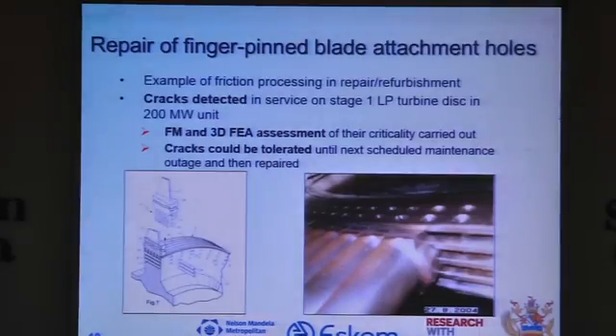The first case study I've got here for you is a repair of fingerpin blade attachment holes. We detected cracks on these discs. Did our fracture mechanics calculations, did our 3D FEA work, saw that the cracks are not critical, but they will be critical at the next shutdown. So you're sitting with a crack that you can tolerate, but within a few months' time you're going to need a solution on the table. The photographs at the bottom are just there to show you the complexity of the curvature of the attachment of these blades.